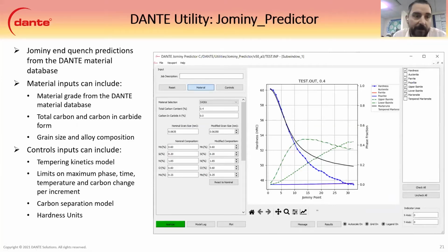For Jominy, Jominy does the Jominy end quench predictions. So what we'll get here is we'll get the individual phases over Jominy point. Jominy point is depth, and I believe each one of those is about 1/8 inch. So your material inputs are exactly the same. You know, from the database, choose it. And then it runs the Jominy end quench.